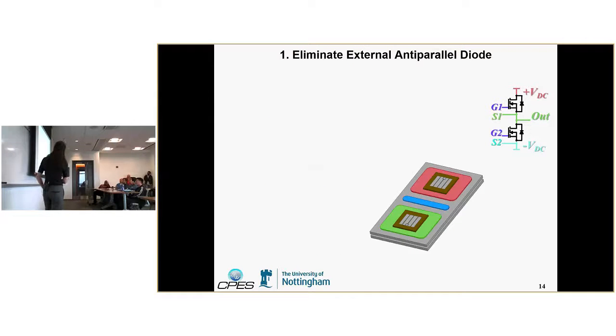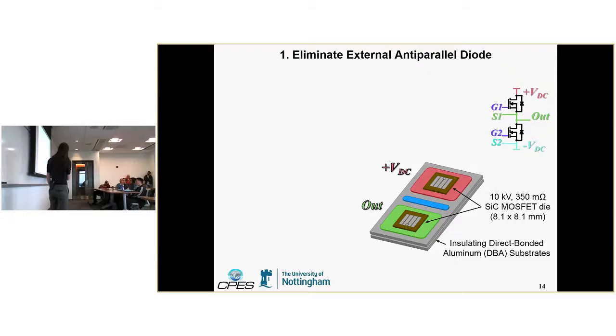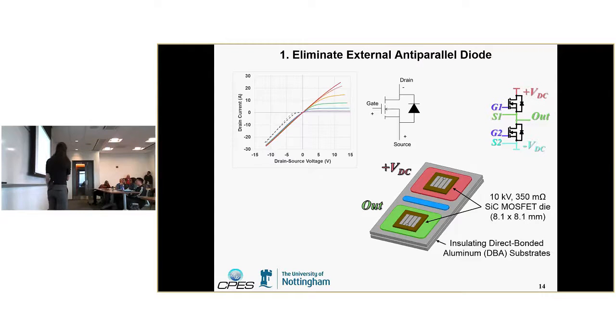Okay, so this is the designed power module. I'll go through it in phases and build it up as we go. It's a half-bridge power module, so there are two silicon carbide MOSFETs here, one here and one here. And then we have at the bottom the insulating substrate, and these colors correspond to the nodes in the schematic at the top right. So we've got the high side switch and its drain contact, and the low side switch and its drain contact. And these are 10 kV 350 milliohm silicon carbide MOSFET die.